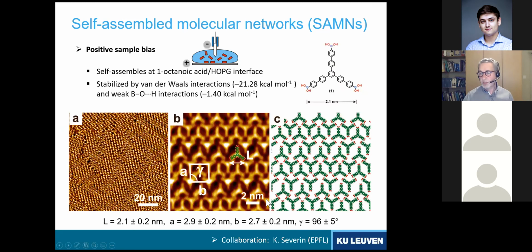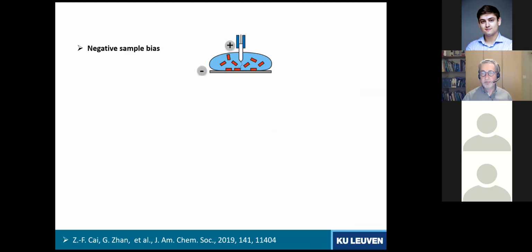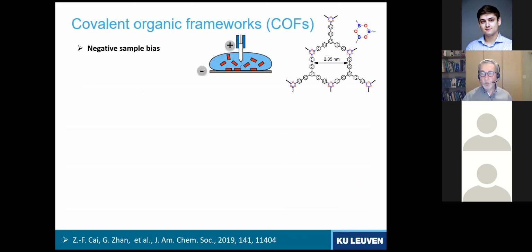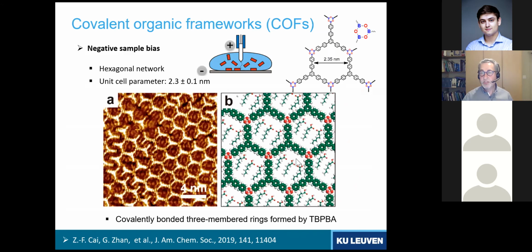So these are, of course, the scales. So this is a high resolution image or a zoom of it. This is just one molecule, and it forms a self-assembled network. But it actually came to us as a quite pleasant and unexpected surprise that when we change the sample bias from positive to negative, something else happens. Namely, we get a different structure, but a different structure which is not supramolecular in nature, but which is covalent